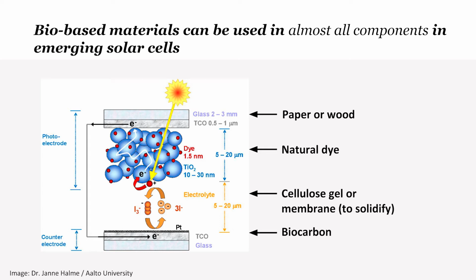When the dye converts a photon into electricity, the electron transports through the titanium dioxide film to the conducting layer of the photoelectrode, where we have this conducting transparent oxide on top of typically a glass substrate. The charge is then carried to the counterelectrode, where we have another conducting glass and catalyst, typically platinum catalyst, that helps transfer the charge from the counterelectrode to the liquid electrolyte, which then returns the charge back to the photoelectrode.